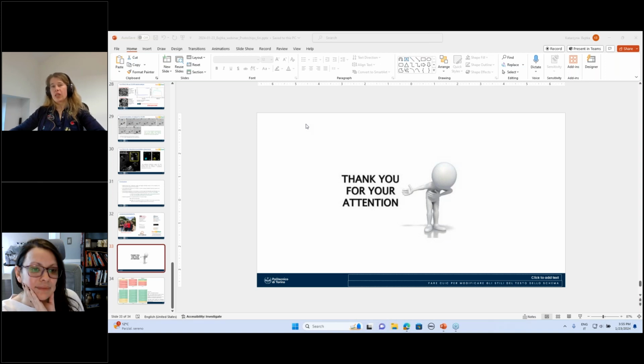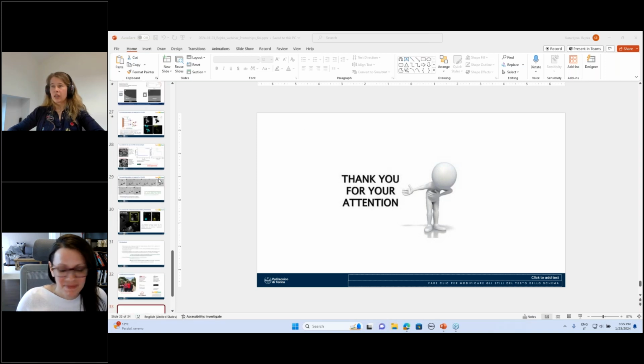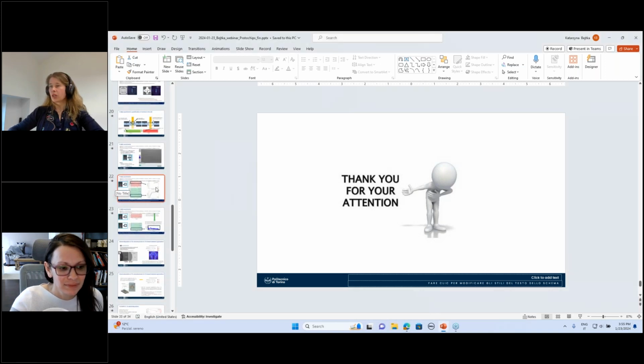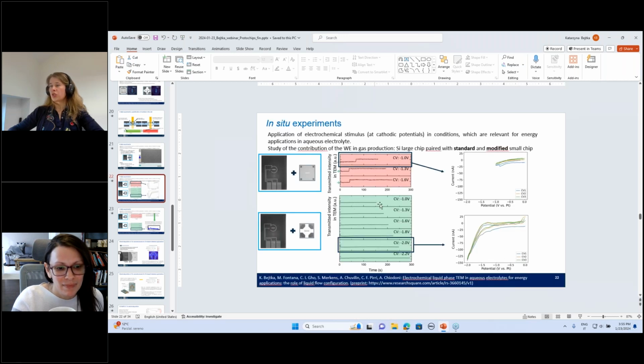We were able to produce the bubbles on demand when we wanted to do some more high resolution imaging, and then we were producing the bubbles with more negative potential. But at the potentials of interest, the potentials that I have shown you, we were able to keep the cell fully filled with liquid, or at least most of the time. Great, and that was even with using a gas-saturated electrolyte? Yes, yes. All the experiments that I have shown, like the comparison experiments, were all performed in the electrolyte saturated with CO2. Perfect. Wonderful.